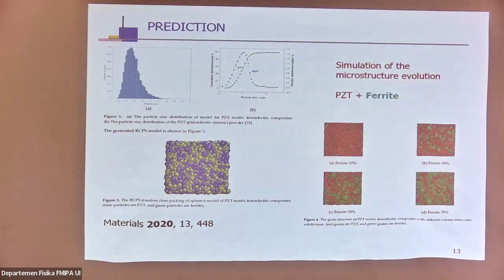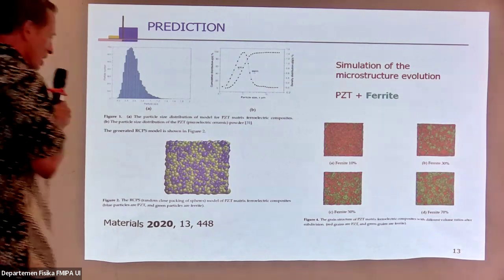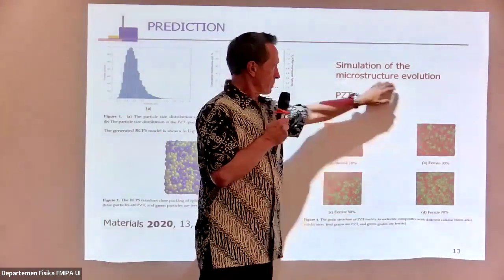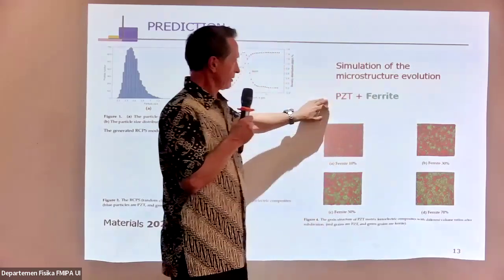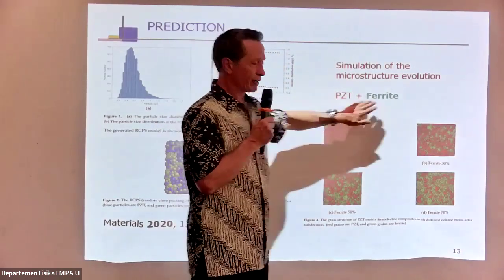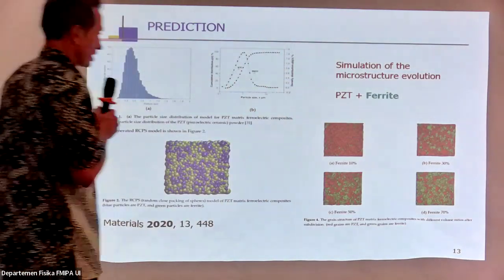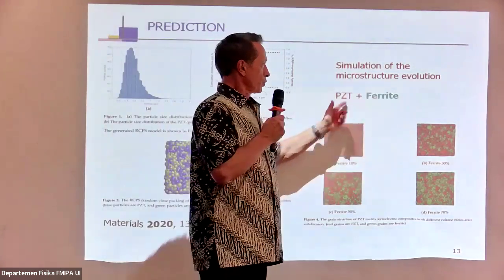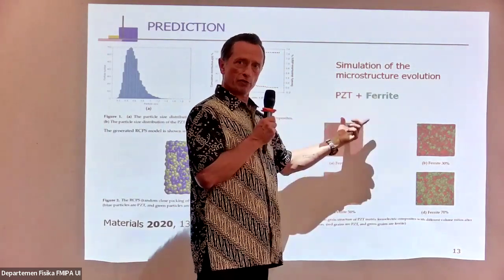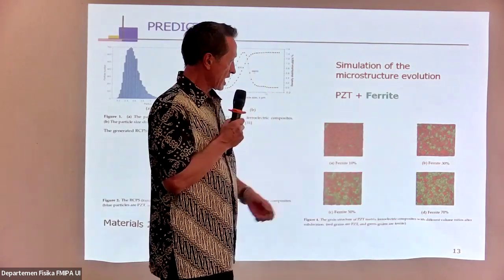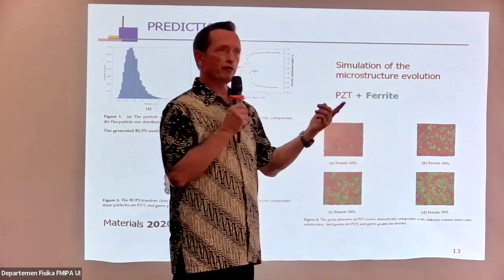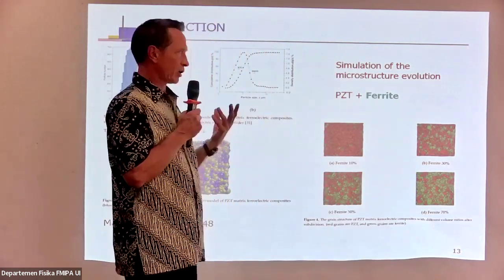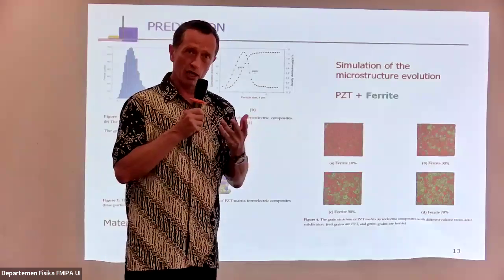And recently, there is also a huge and intense activity of the researchers about the study of mixed materials, mixed oxide between ferroelectric oxide and ferrite. And when you mix this kind of material, you can have different cases because you will tune finally the percentage of each material in your final structure. And simulation can be very efficient to predict the properties of your material and, of course, the trouble you can be able to observe later by experiment.